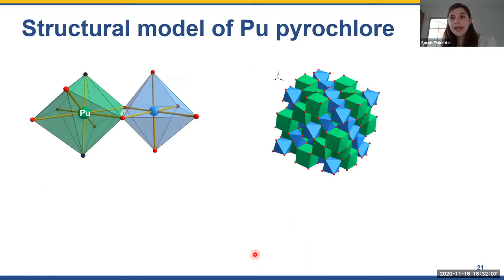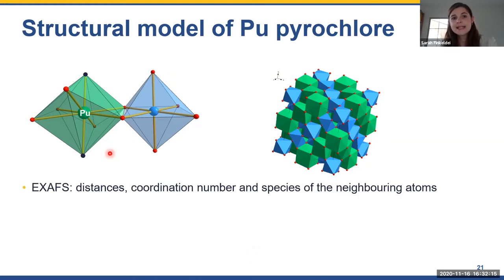In order to analyze the EXAFS data, you need to come up with a structural model of your plutonium pyrochlore to fit your data. What we did is we built a structure where we set the plutonium, even though it's a plutonium 4, let's try to see if it's localized at the A site. And the A site, if you remember, is 8-fold coordinated by two Y oxygens, which are a little bit closer to the plutonium cation, and the 6 X oxygens, which are a little bit further, kind of this chair conformation, if you remember your sugar classes in chemistry.